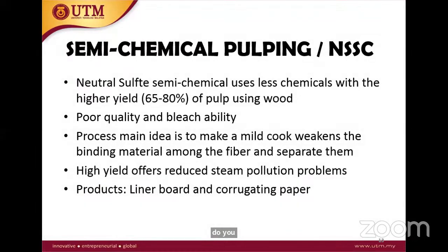Semi-chemical pulping (NSSC). The process will use less chemical with a higher yield, which is 65 to 80% of pulp. This process is based on wood material. It has poor bleachability, which also affects the bleaching process. The main idea of this process is to make a mild cook among the fibers in order to separate them. The high yield offers reduced effluent problems. The products are linerboard and corrugating paper.